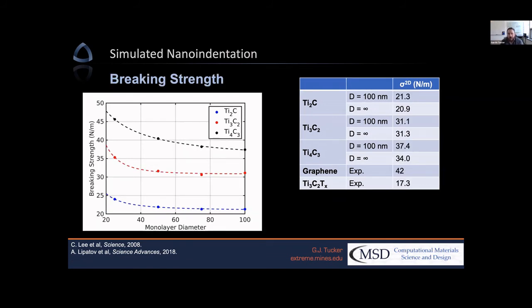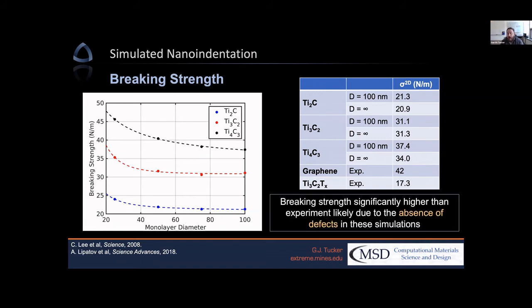Now, if we move on to breakage strength, we can do the same thing for breakage strength here. And if you look at the chart on the right, what we end up seeing is that our simulated calculated values are actually significantly higher than experiments. And that is likely due to the absence of these defects in the simulations that we talked about earlier.